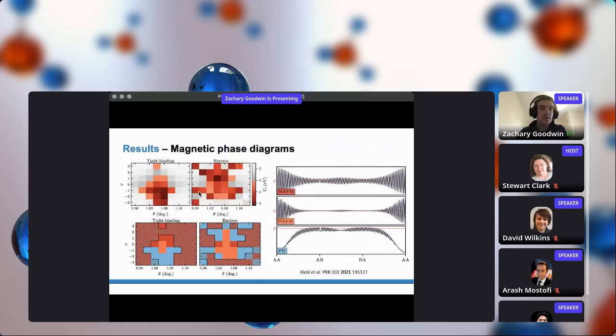Right, so what I'm showing here is the results of our analysis in the 2 approximations, so the tight binding without long-range electron interactions and with these long-range electron interactions. As you can see, the red regions are where we expect magnetic order to occur, so the critical Hubbard on-site interaction is lower than 4 electron volts. And you can see that these 2 approximations are really quite different. In the tight binding, we essentially have magnetic order just right around the magic angle for hole doped systems.